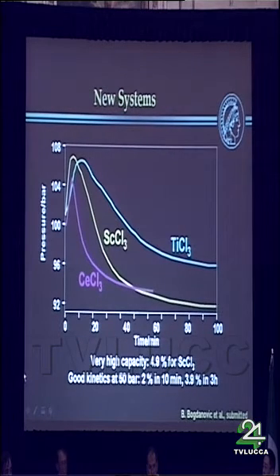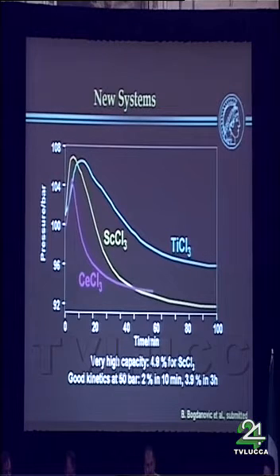That's what we thought until we re-examined some of the rare earth elements, and we actually found that scandium and cerium are superior to titanium. So these are all identically synthesized titanium trichloride, scandium trichloride, cerium trichloride. The scandium and the cerium have quicker kinetics than the titanium trichloride as catalysts, and especially for the scandium chloride, the capacity is basically at the theoretical limit. So it's 4.9% consistently over many cycles, reversible capacity at these rates.